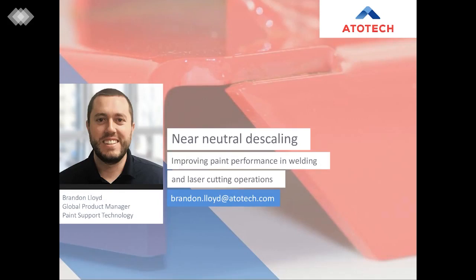Yeah, so similar to what we've seen in the slides for the heat affected zones, this would definitely be achievable with these type of products. And what we saw from some of the E-coat evaluations, we see a significant improvement in the paint adhesion, especially even for the single coat E-coat application where we evaluated. We see quite a nice improvement as compared to no descaling at all.